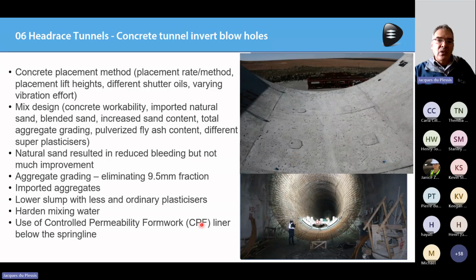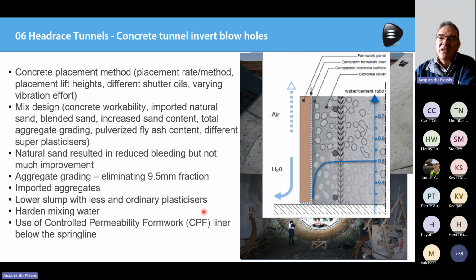So what was specified is a controlled permeability formwork liner, but it's expensive. And it takes time every time to fix to the shutter, because you can use it once, maybe twice, and then you have to replace it. So you can understand why the contractor tried his best not to place the CPF liner. So what is a CPF liner? There's the shutter. You fix it to the shutter, and then you place and vibrate your concrete against it. So the air can escape through the liner and the water drains out.